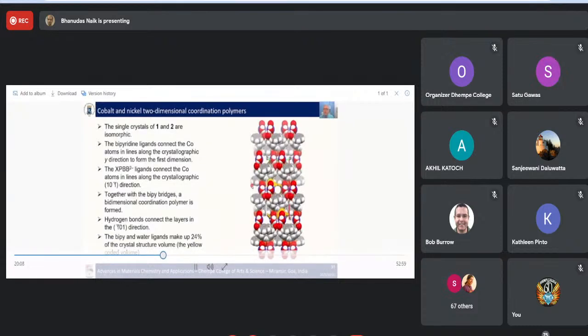And if you remove the BP and the water molecules, you actually have quite a bit of space inside. You can see the space here, and this is mapped out in Mercury in this yellow form here. It's a bit difficult to see. But Mercury calculates that about 24% of the volume of the crystal structure is made of the BP and the water molecules. So you can have quite a bit of porosity if you manage to remove the BP and the water molecules without the collapse of the structure.